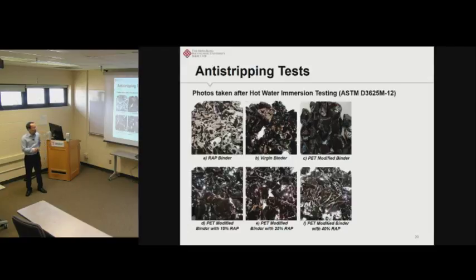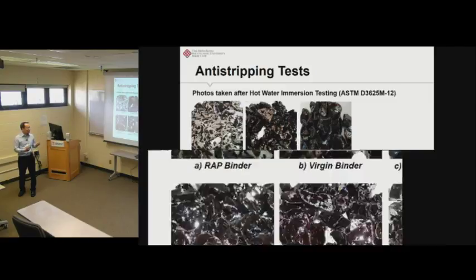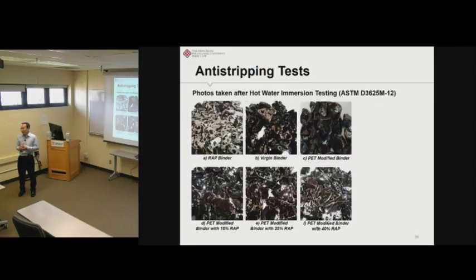And the third one is the aggregate with the PET modified binder. You can see the difference. So compared with the virgin binder, it's even better. We can hardly see any binder loss after the test. So in the bottom you can see the aggregate coated with the PET modified binder with different percentages of wrap binder. The first one with 15%, 25%, and 40%. If we have 40% of wrap binder, usually we can consider it as a high wrap mixture.